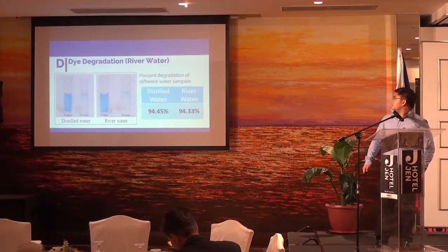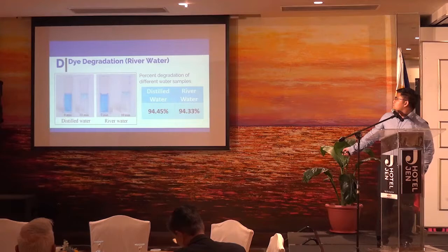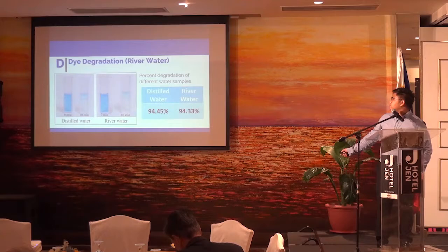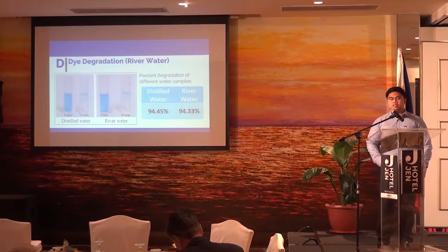For the actual real water sample from the river, we compared results from distilled water versus the river water sample. We yielded 94.45% for the distilled water, and for the real water sample we have 94.33%. Comparing through statistical testing, we can further claim that there is no significant difference between the two, which means we can apply this study on real water samples.